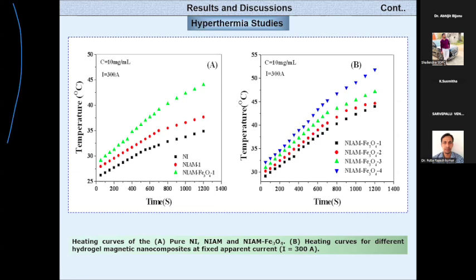So in the first graph we have compared NIPAM polymers with nanoparticles. Now we have developed hydrogels with variant amounts of iron nanoparticle concentrations. We are seeing that wherever the nanoparticle concentration in the gel is higher, it gives very robust performance.